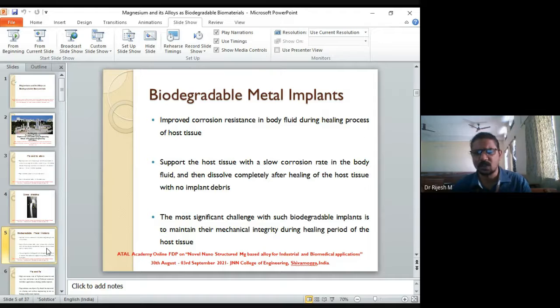You can only do one thing. You can reduce the rate at which corrosion takes place. Titanium is a wonderful metal where your corrosion rate is too small. Actually, the amount of material that corrodes in titanium is so small that we generally have to go for a Tafel extrapolation plot to find out how much material is getting corroded.